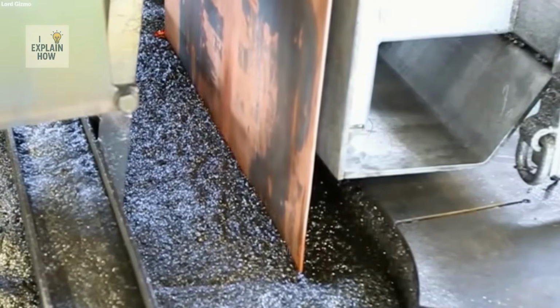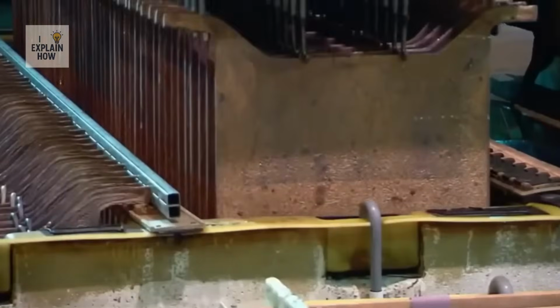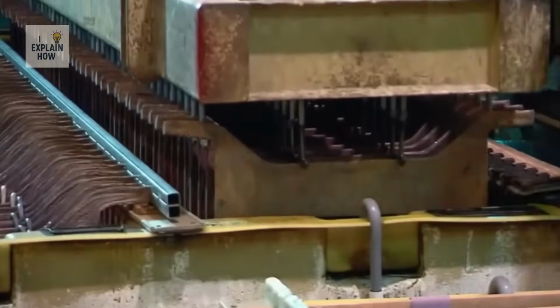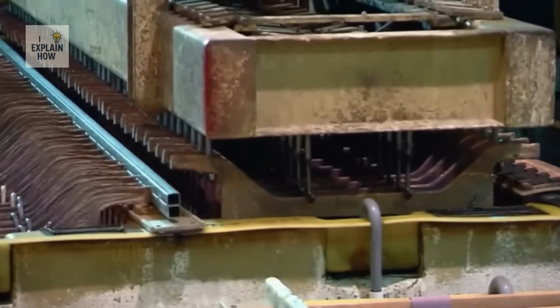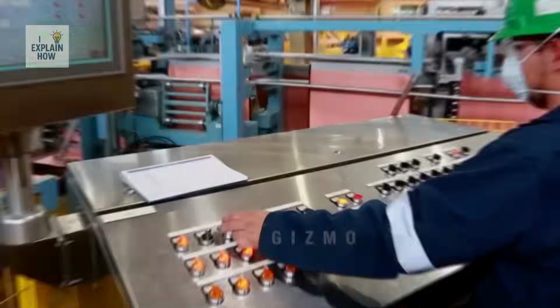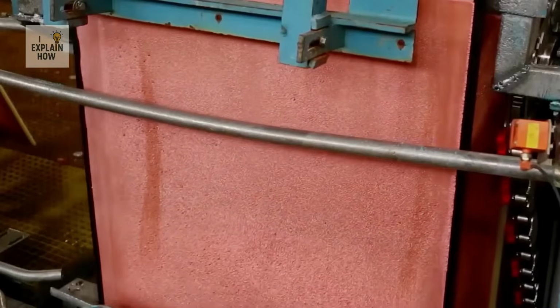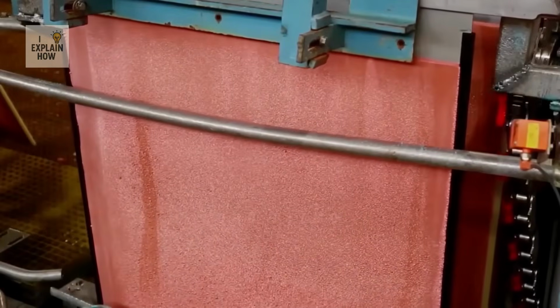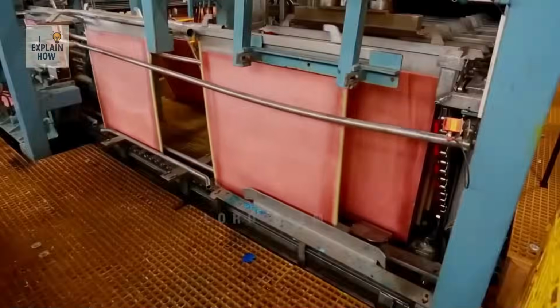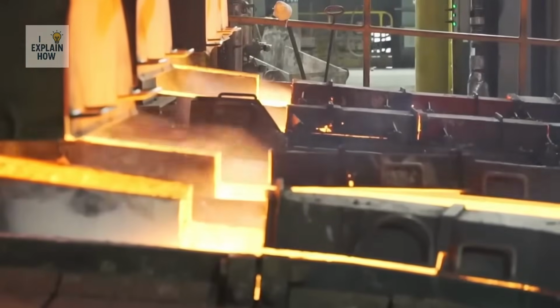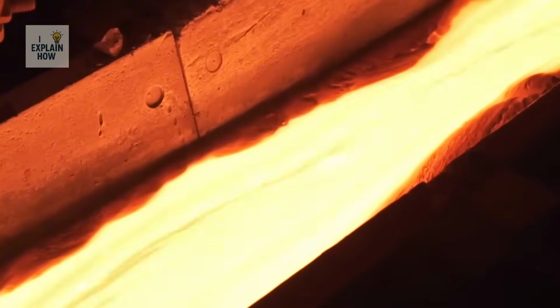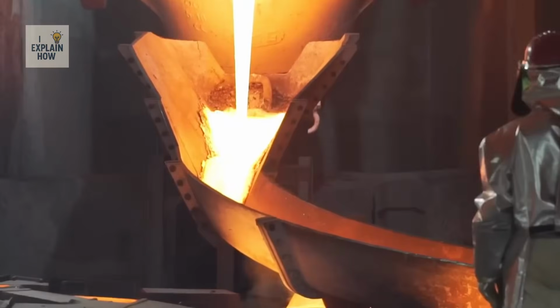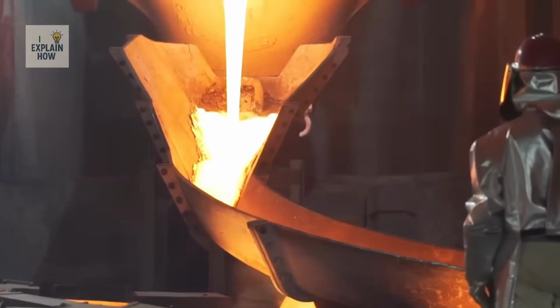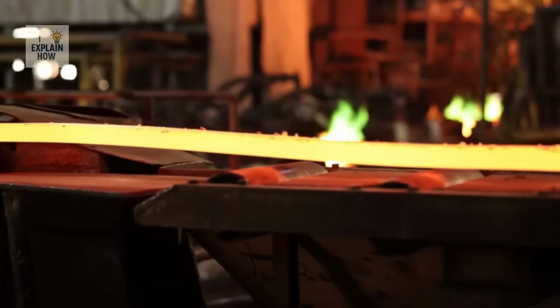In the refinery, purity reaches its maximum. The anodes are immersed in large tanks containing an electrolytic solution and placed opposite thin metal strips called cathodes. When an electric current is applied, pure copper transfers from the anodes to the cathodes while impurities fall to the bottom of the tank. The result is copper of near-perfect purity, ready for use in the most demanding electrical applications.